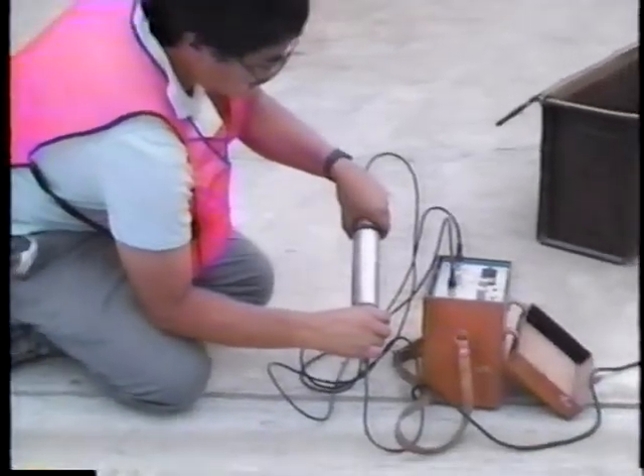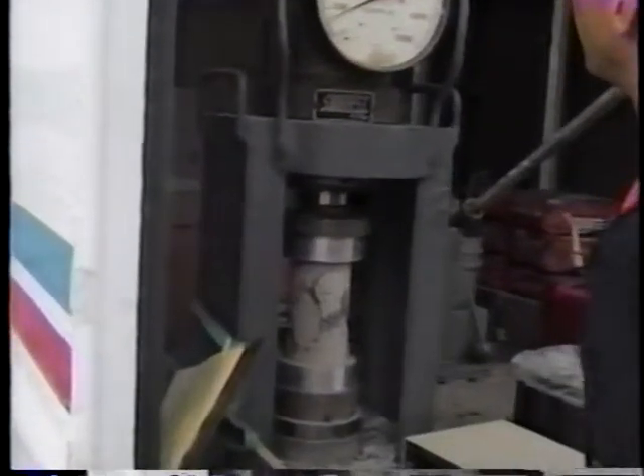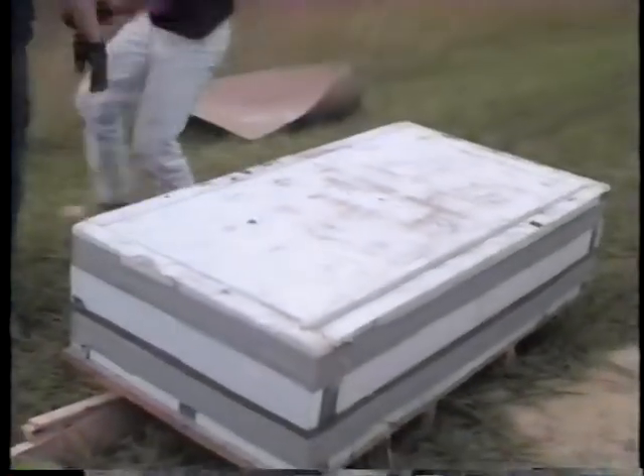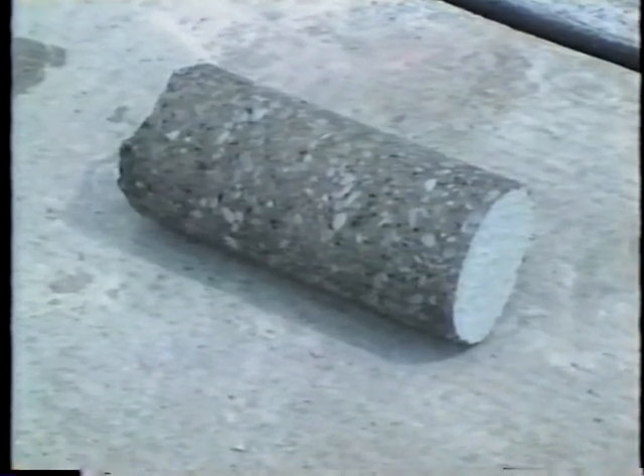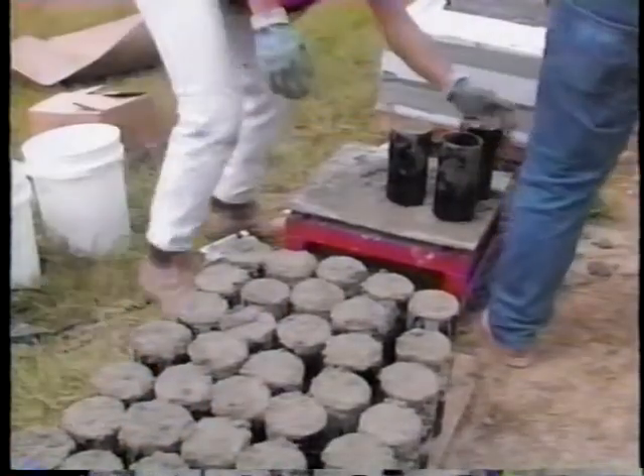Each also requires instrumentation to perform the testing. The destructive testing procedures involve field testing of either concrete cylinders, which can provide either compressive or split tensile strengths, or concrete beams, which provide flexural strength. It is well known that the in-place strength of concrete at early ages is much greater than that indicated by field cylinders. Several procedures can be used to estimate the in-place strength of concrete repairs. These include temperature-matched curing boxes, insulated cylinders, and cores. Field testing results showed that concrete cylinders placed in an insulated box provide a satisfactory indication of strength gain in the repair sections.